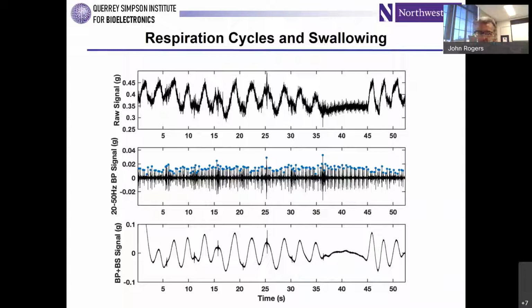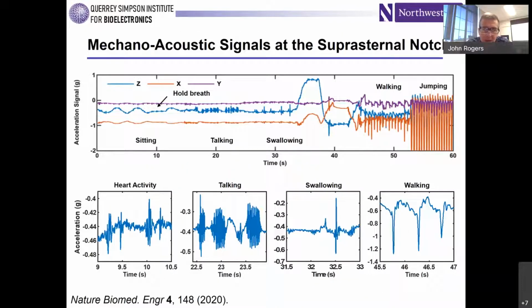But then you also see these sharp events periodically riding on top of those respiratory oscillations. Those are swallows. You can determine when an individual is swallowing, and also when they're swallowing relative to the respiratory cycle. And it turns out that's very important information as well, because if you swallow at the wrong point in a respiratory cycle, you can choke yourself in ways that can be very dangerous. So these are the kinds of data streams that emerge, and they're all separable.